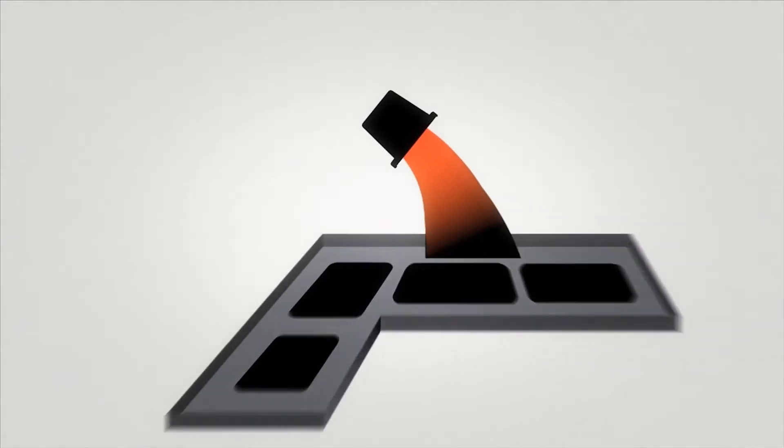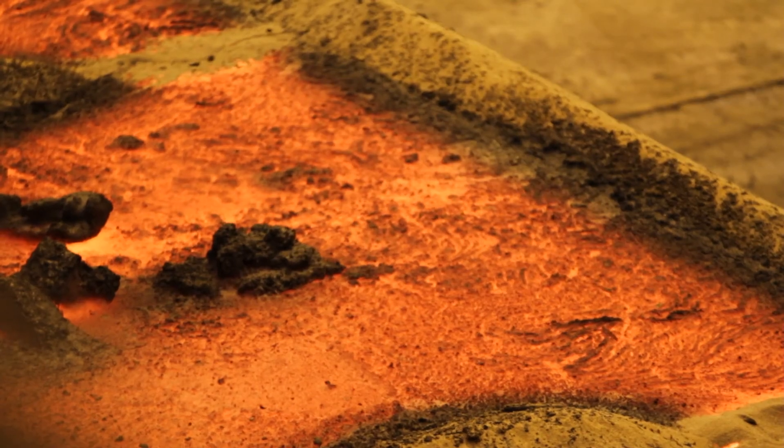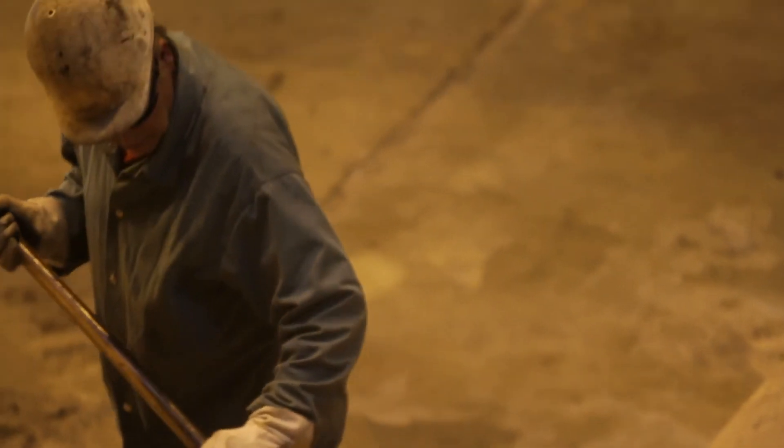The alloy is then poured into prepared casting pits. The ferro-manganese product undergoes an additional step of refining into medium carbon and low carbon product before being cast.